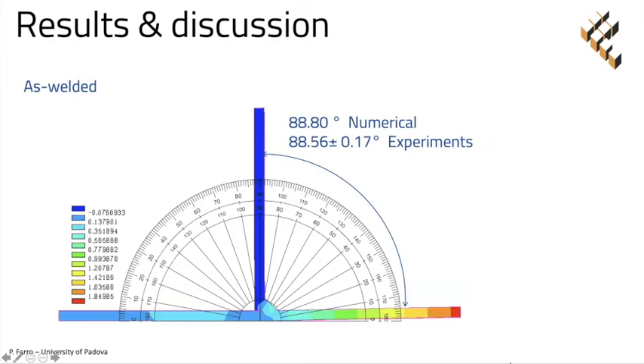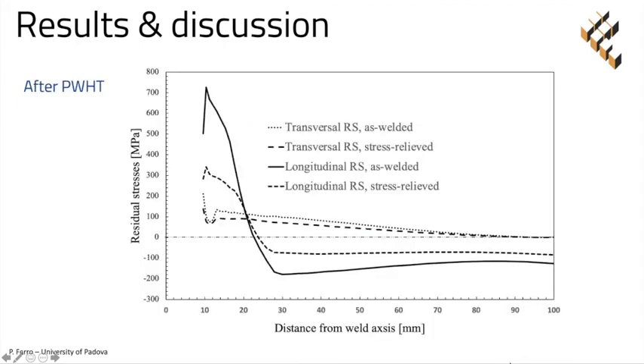After welding, the angle between the flange and the web obtained by the numerical model was 88.8 against an experimental value of 88.56, which is considered a reasonably good result. After stress relief heat treatment, the distortion angle didn't show any variation, and the numerical results confirmed that experimental evidence. However, residual stress reduced significantly as shown in this figure.